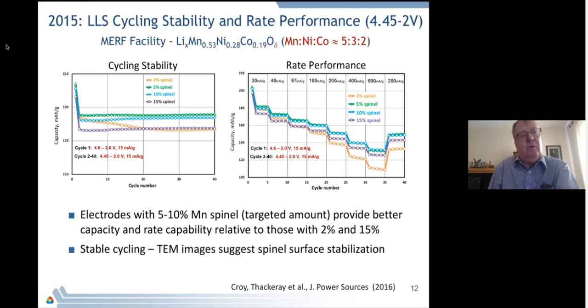So we've advanced our knowledge of these materials, and by 2015, we had scaled up some of these materials and had discovered that if one introduced between 5 and 10% spinel, which you can see in the green and the blue plots, on the left-hand side, both cycling stability and on the right, rate performance of these materials is considerably improved if you have between 5 and 10% of spinel within the structure. TEM images, however, have demonstrated that it's more likely that the spinel in these cases is found at the surface rather than within the bulk.